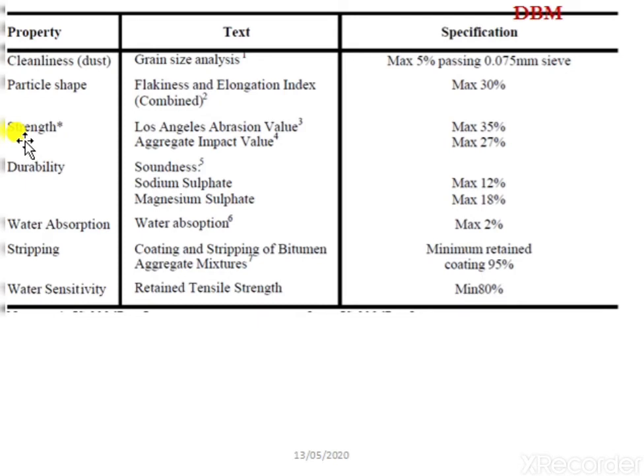The next property is strength. To determine the strength of the aggregate, the tests conducted are the Los Angeles abrasion value test and the aggregate impact value test. The strength of the aggregates is determined based on the values of these tests. The Los Angeles abrasion value should be within 35%. Then only can the aggregates be effectively used in construction. Similarly, the impact value of the aggregates should be less than 27%. If it is more than 27%, then the materials can't be effectively used in the construction of DBM.